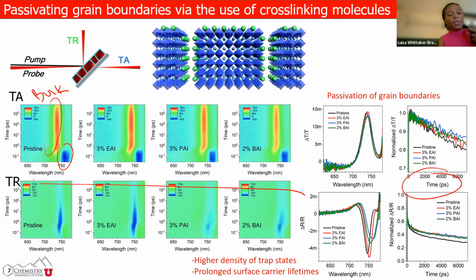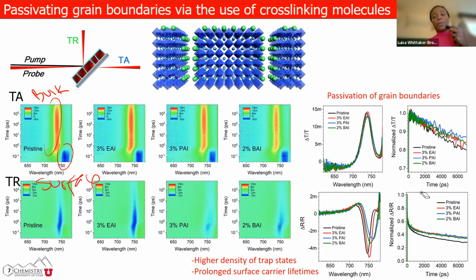So now with transient reflection, what I'm doing is just looking at the surface, right? And again, if we focus on the lifetime, then you will notice that there is a faster lifetime for the reflection data. So whatever is happening in these materials at the surface is faster than whatever is happening in the bulk. This is, again, an indication that my surface has way more defects than the bulk has. But at the same time, we see that there is an increase in the lifetime here, which again is an indication that we have a higher density of defects at the surface, but we are passivating those with the alkyl ammonium cations as well. Okay? So, all right.